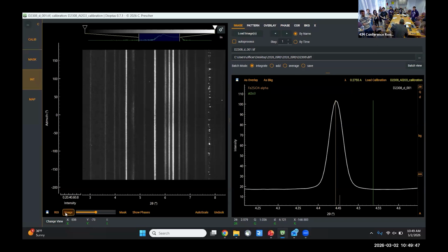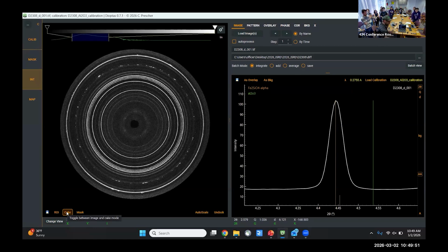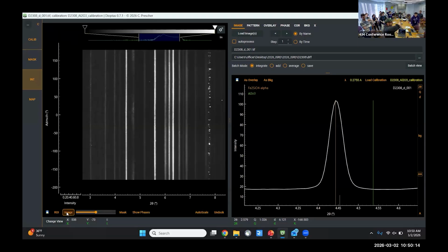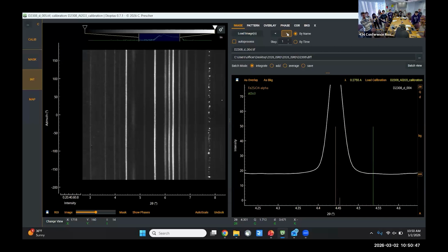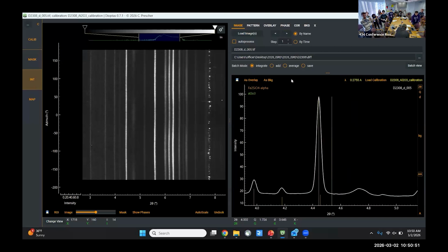Okay, so this is what our image actually looks like. It's the circles. But sometimes, since they always have the same radius, we'll plot it with the angle on the y-axis versus the distance. So this distance here is 2 theta. If we do that, it's kind of like unwrapping that circle. So now we have the angle around our circle versus the radius of our circle. And because the sample is not under any pressure, these will be completely straight lines. Actually, why don't I just show you when they start to get stressed. This is a different material, but now we're increasing the pressure.